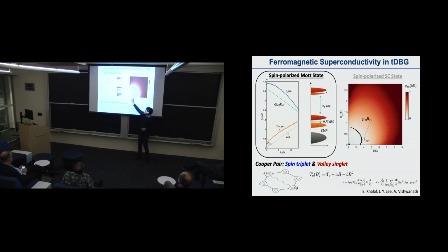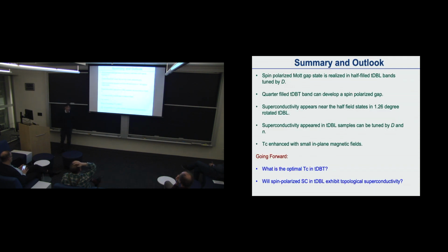A strong indication is that you'd expect a linear increase of the TC with the magnetic field, and the slope should more or less fit with the Zeeman energy. Indeed, we confirm this: if I fit this linear curve, it matches what we'd expect from the Zeeman energy, strongly suggesting—though still indirect at this point—that this is spin-polarized superconductivity in this system. At this point, this is just a status report.